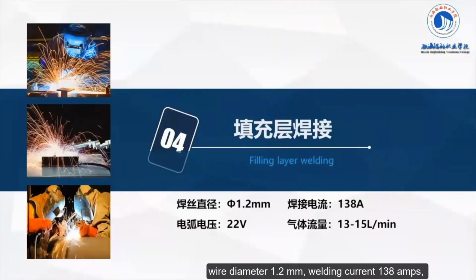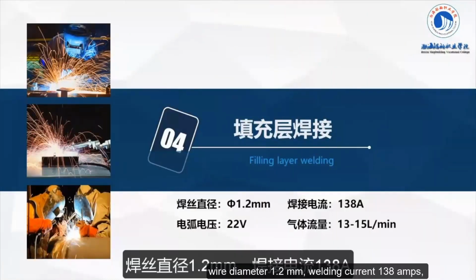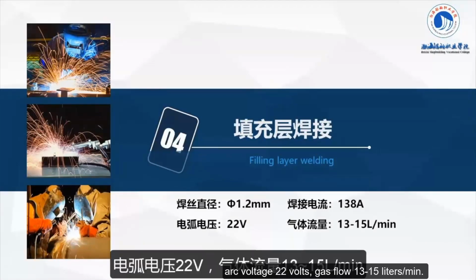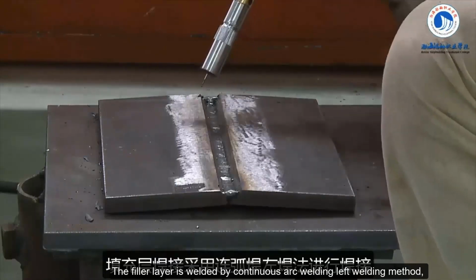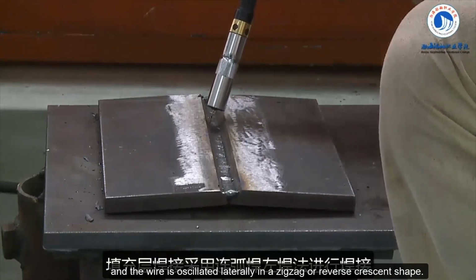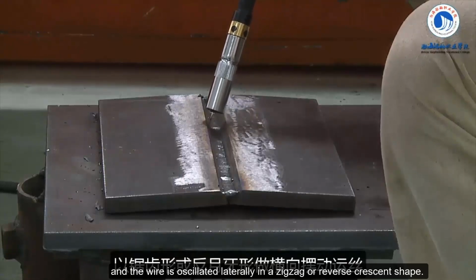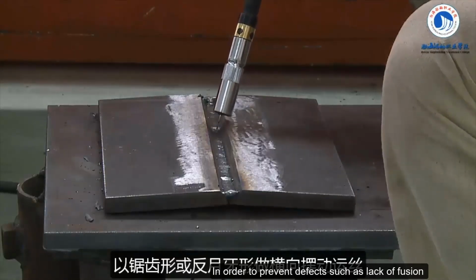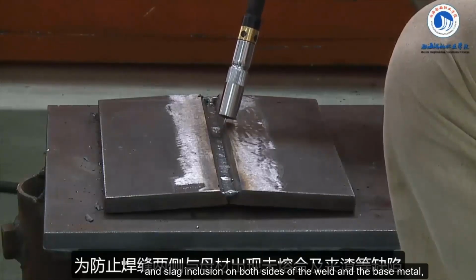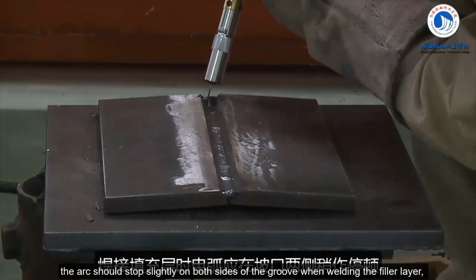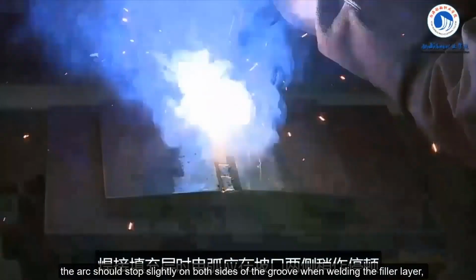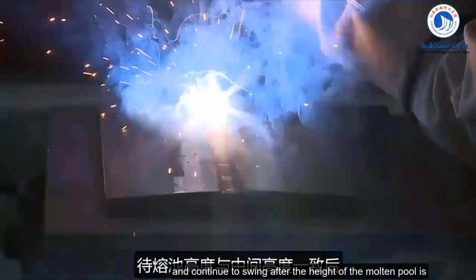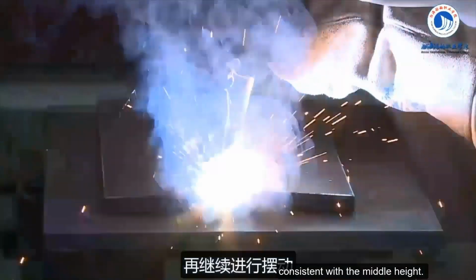Filler welding. Wire diameter 1.2 mm, welding current 138 amps, arc voltage 22 volts. Gas flow 13 to 15 liters per minute. The filler layer is welded by continuous arc welding left welding method, and the wire is oscillated laterally in a zigzag or reverse crescent shape. In order to prevent defects such as lack of fusion and slag inclusion on both sides of the weld and the base metal, the arc should stop slightly on both sides of the groove when welding the filler layer, and continue to swing after the height of the molten pool is consistent with the middle height.